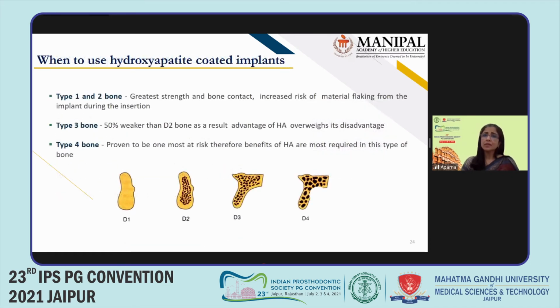However, there are some concerns regarding these coatings, which include microbial adhesion because the surface is very rough, and you could also have osseous breakdown. Most importantly, something that's really a concern for many clinicians, and also a reason why many clinicians have stopped using the hydroxyapatite coated implants, is the failure of the coating itself. Okay, so when do we use the hydroxyapatite coated implants?